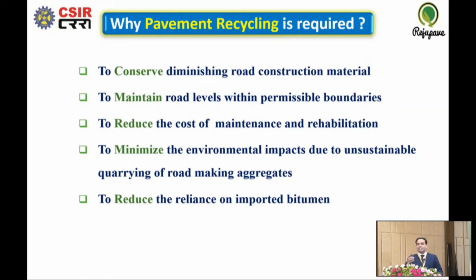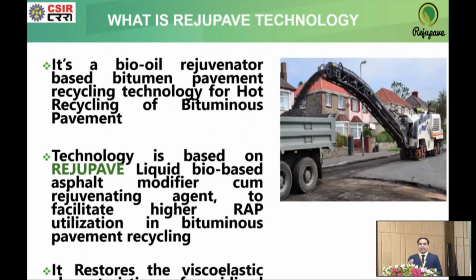For your information, I just want to brief about reclaimed asphalt pavement material. The RAP is primarily a composition of natural aggregate and oxidized binder. When you mill the distressed bituminous surfaces, RAP will be extracted, which comprises the natural aggregate and oxidized bitumen binder, and this binder in the RAP may be in the tune of 3 to 4.5%. With the help of this Reju-Pave rejuvenator, we can replenish the oxidized properties of bituminous binder and we can reutilize it in the fresh bituminous mixes. Parallelly, we are reusing the natural aggregate which we have retrieved from the distressed surface. Besides that, the bituminous binder, which is almost dormant in condition, we can reactivate it and reutilize it in the bituminous